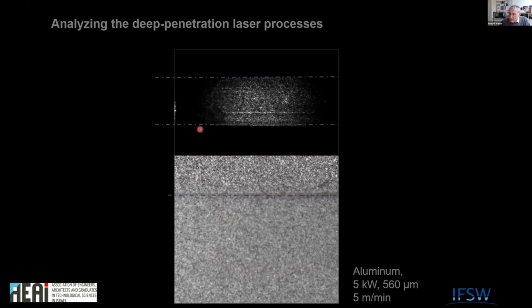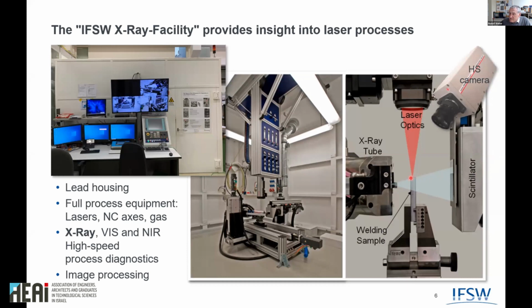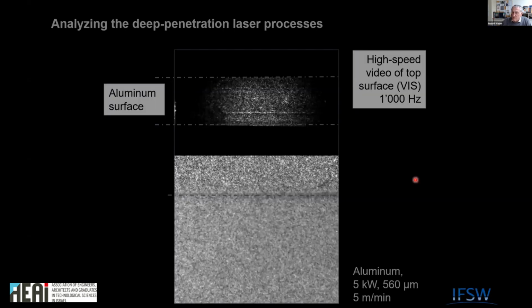Let's go back one picture again, sorry. Here you can see this is a typical sample. This is the surface. The laser comes from the top. The X-ray comes from the side. And the high-speed camera looks from the top. So what you can see here is the surface of the sample. In this case, it was aluminum.